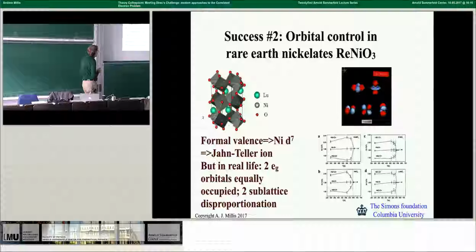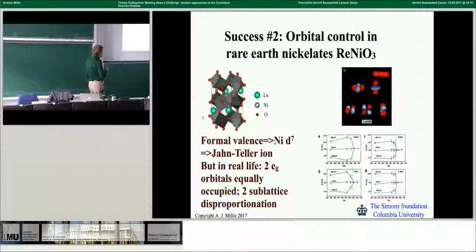Now, this transition is a bit surprising, and there's a story here that I'm not really going to have time to tell you. The formal valence of this nickel is d7. That means there's an odd number of electrons in the d shell, and in particular, let's say the t2g xz, yz, xy orbitals are completely filled, and notionally there's 1 electron shared amongst the x squared minus y squared and 3z squared minus r squared orbitals.